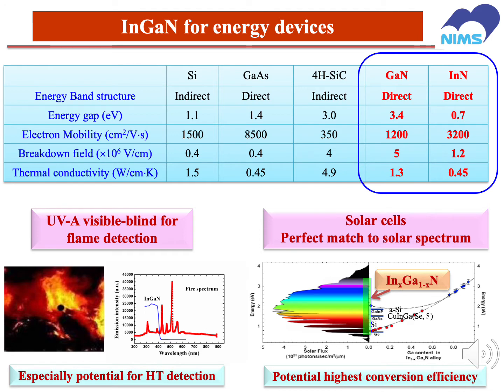If we use InGaN for UVA and visible-blind photodetection, it is very promising for flame detection because it has very good physical and chemical stability, especially for high-temperature detection, which I will show later. Also, as I introduced, InGaN has a perfect match to the solar spectrum, much better than other material systems. And then I will show our results on InGaN solar cells.